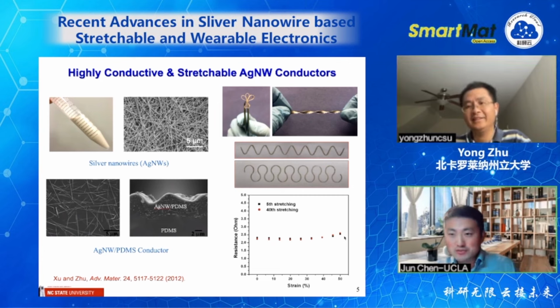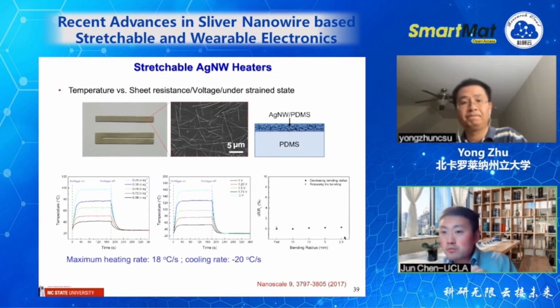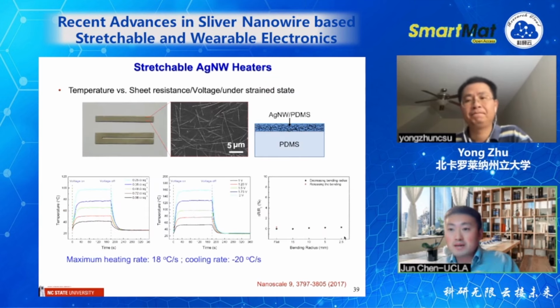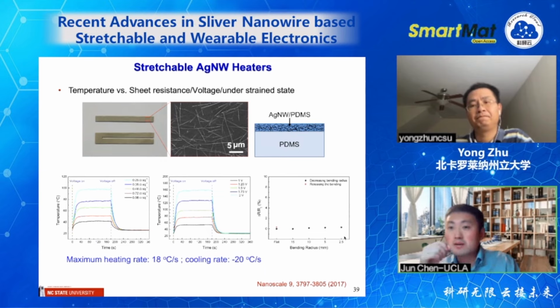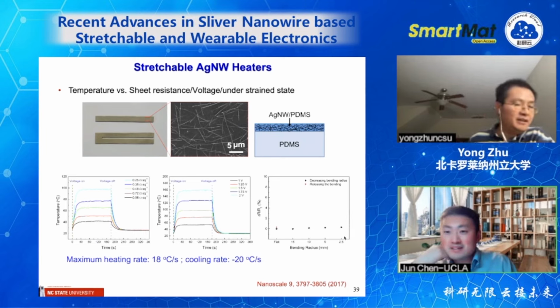Okay, thank you. There's another question from the audience about the wearable heater. From the performance we can show the heater could heat up to 160 degrees C. Is this performance reliable? Because the silver is embedded in a polymer matrix, this kind of high temperature will change the resistance of the silver nanowire and also the interaction between the silver nanowire and the polymer matrix. Okay. Very good question.